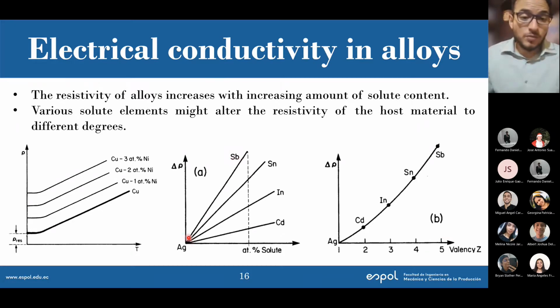You can see for silver, the higher the concentration in atomic percent, obviously the higher the resistivity, and that happens for all of them. And you can see that cadmium has the lesser effect, and that's because cadmium is only a bivalent metal compared to indium or tin, which are 3-valent or 4-valent metals. So there is a shift on the resistivity versus temperature curve if I increase my solute content.